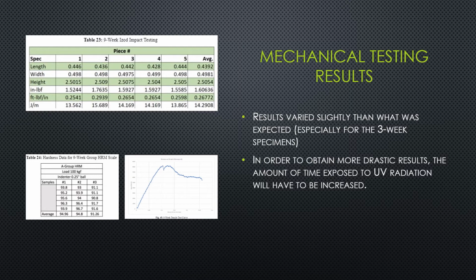We found that this could be possibly true since the material is a UV curable photopolymer, thus being in the UV exposure box for the 3-week period of time could have given the material enough time to cure and increase the mechanical testing results, with this having a higher impact resistance, higher tensile strength, and increased hardness for that 3 week period.